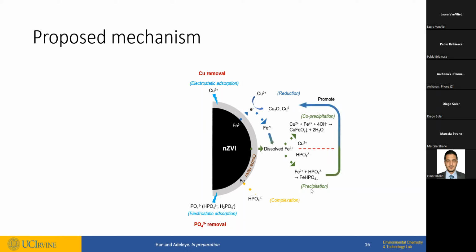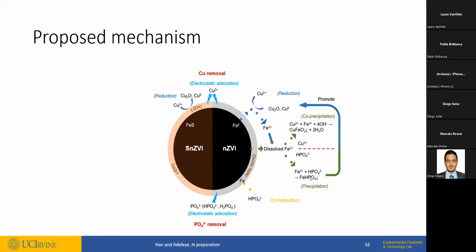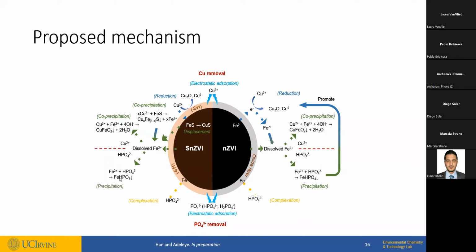And we think that is exactly how the two contaminants are promoting the removal of each other, because the product of the removal of one is the reactant for the removal of the other. For the sulfidated iron, the story is not much different. We have adsorption, we have reduction, we also have displacement. All of that generates some dissolved iron, and some of the dissolved iron goes to precipitate copper. There's also the second co-precipitation, which also generates some dissolved iron, and that iron now goes to the precipitation of phosphate. So again, the product of copper removal is a reactant for phosphate removal, and that way they are both synergistically being removed essentially. So we think that's the story here, and that's why we think that NZVI is way more effective when the two contaminants are present.